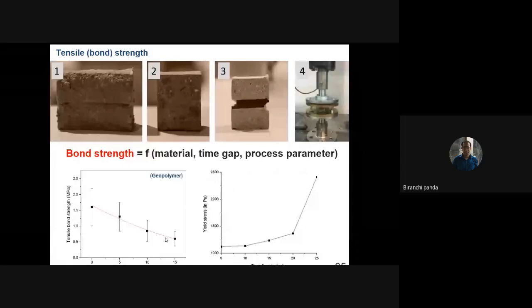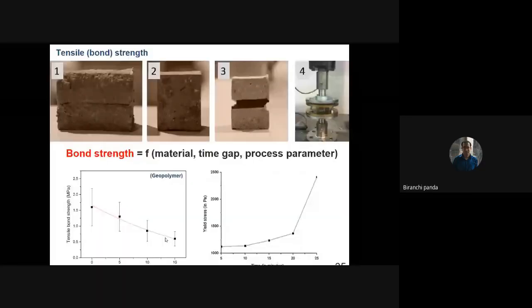Suppose you are doing a very large scale printing. You print one layer, it takes about 1 minute. Now for printing another layer, you have to wait for 1 minute. So it means the time gap between these two layers is almost 1 minute. Similarly, if you print a smaller object, the time gap can be reduced. So we tried to investigate how this time gap is affecting the bond strength. And as you can see in the results, with more time gap, the strength becomes very low.